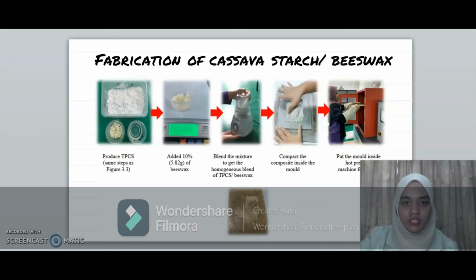Okay, this is fabrication of cassava starch and beeswax. Start with producing TPS, and then we add beeswax, blend the mixture to get a homogeneous blend, compact it into the mold, put the mold in the hot pressing machine for 1 hour, and we got the sample.